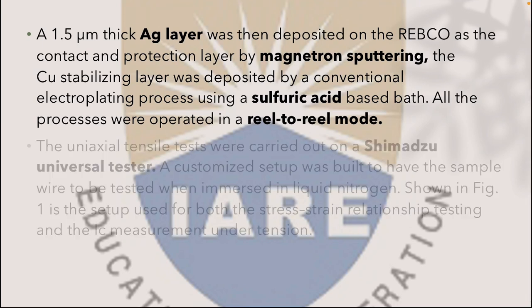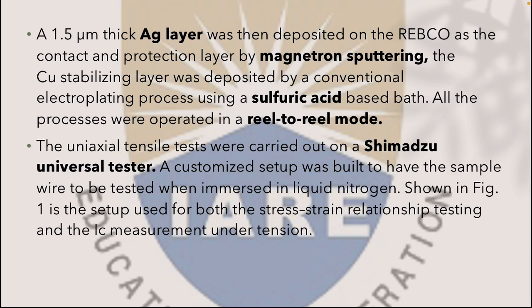A 1.5 μm thick silver layer was then deposited on the REBCO as a contact and protection layer by magnetron sputtering. The copper stabilizing layer was deposited by a conventional electroplating process using a sulfuric acid based bath. All the processes were operated in a reel-to-reel mode. A uniaxial tensile stress test was carried out on a universal tester. A customized setup was built to have the sample wire tested while immersed in liquid nitrogen.